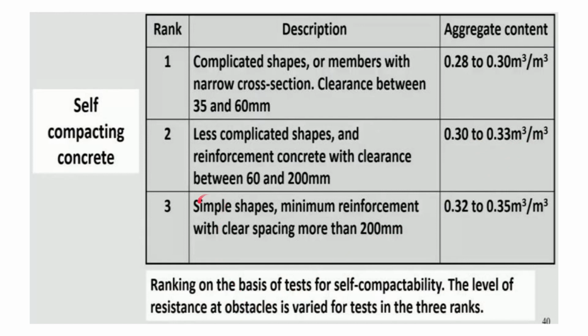And if the shapes are further simple and the minimum reinforcement with clear spacing is more than 200 mm, then we can further increase the aggregate content from 0.32 to 0.35 meter cube per cubic meter of concrete. So these criteria can be adopted. Ranking on the basis of tests for self compactability, the level of resistance at obstacles is varied for tests in the three ranks. For the various types of obstacles and resistance, they are varying, and that's why the self compactability parameters are also ranked differently.